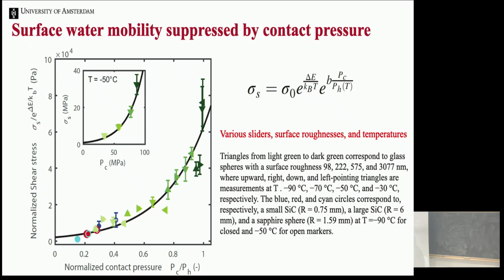And so here we say that this exponential factor is actually proportional to the real pressure over the penetration hardness, because that gives the difficulty with which the molecules can move. And so if I then plot my measured shear stress, so the friction force basically per unit area, as a function of the contact pressure that I now have inferred from my finite element calculations, I actually get a very nice agreement.